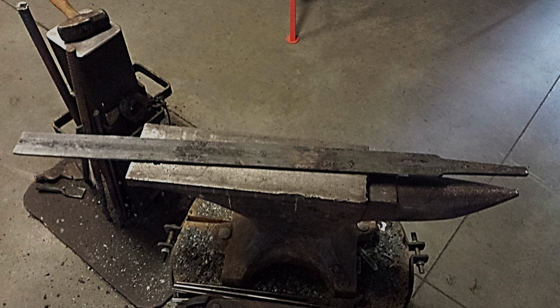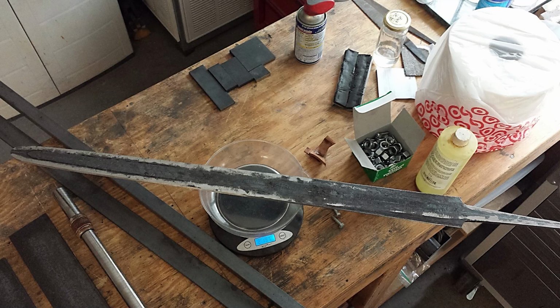Profiling will be done at the grinder. In terms of weight, my calculations were way off. The blade is too heavy. I must admit that I took several shortcuts for this first reproduction. My idea was to gather information about the primary patterns, the chevron and the checkers, and about the precise measurements of the elongations of the patterns during the forging. I did not try to reproduce the serpent in this first attempt. That will be for later.